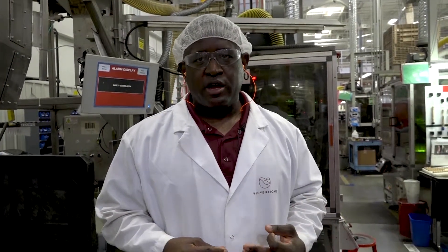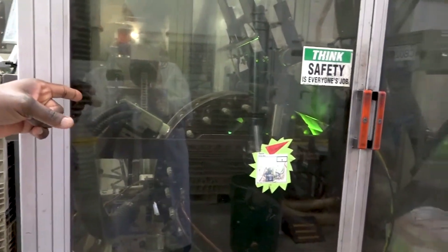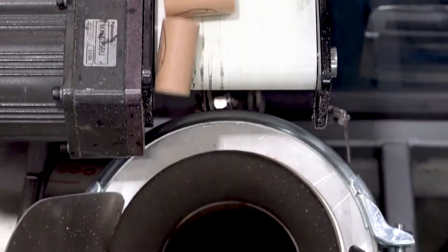After the corks are extruded, the next step is adding a logo — this is our offset printing step. We use a UV-curable ink. The cork is corona treated, which is that electrical charge you see there, and we have a printing plate that allows us to print any type of logo. The corona activates the surface of the cork; without it, the ink would not stick.